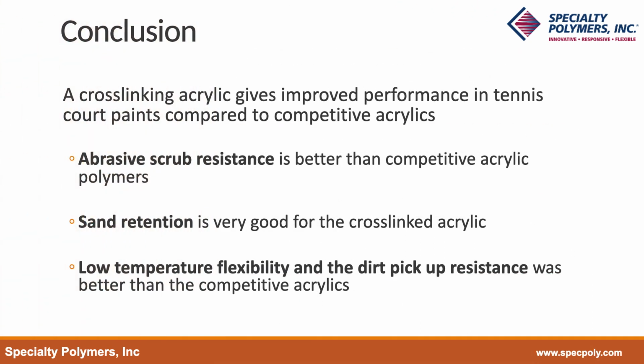Compared to the competitive acrylics, the crosslinking acrylic had much higher abrasive scrub resistance and better Taber abrasion resistance. The higher Taber abrasion resistance for the crosslink polymer formula with sand may also indicate better sand retention, which would give less frequent recoats. Finally, it had very good low temperature flex.